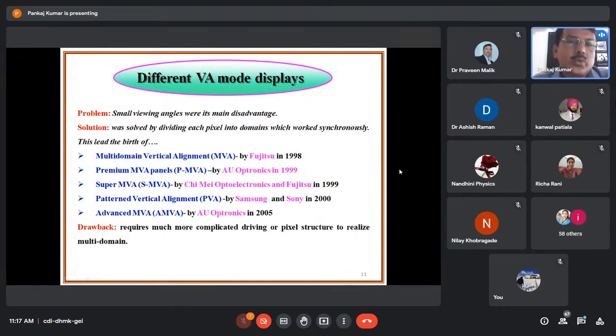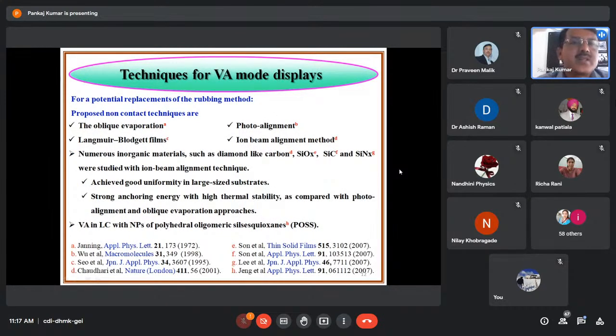However, I would like to share that all these modes of displays require much more complicated driving or pixel structure to realize the multi-domain. That's why all these techniques are also not commercially successful. So for a potential replacement of the rubbing methods as well as these highly sophisticated techniques, there are some other proposed techniques called non-contact techniques, and these include oblique evaporation, photo alignment, Langmuir-Blodgett films, and ion beam alignment method. Numerous inorganic materials such as diamond-like carbon, silica, silicon carbide, and silicon nitride were studied with ion beam alignment techniques. It means these materials were coated on the ITO glass plate with the help of different techniques.